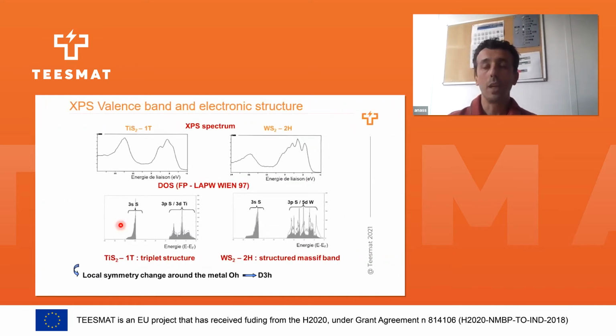Another way to interpret our XPS data is the valence band study, which is not commonly used in XPS. If we look at the literature, there are only a few papers that take care of this part of the spectrum, because it needs some very advanced theoretical support. I will give an example here with titanium disulfide and tungsten disulfide. In this case, we keep the ligand the same, sulfide, but we change the metal, moving from titanium to tungsten. We can see that the signature of the valence band is different when we change the metal surrounding the ligand.